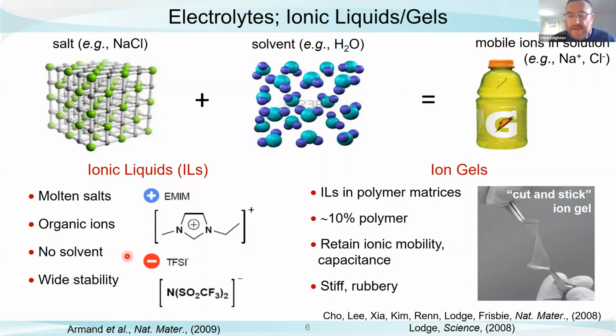The beautiful thing about them is because they're liquid, they have very high ionic mobility, and they have a really wide electrochemical stability window. So we can apply multiple, like 3 or 4 volts, positive or minus, to these materials before they undergo any degradation, okay? You can also make them solid, so you can keep all of the functionality of an ionic liquid. You can bring it into the solid state in a material called an ion gel.